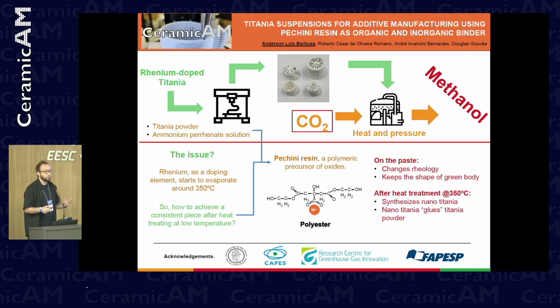And how does it work in our paste? First, this resin works as a rheological agent, changing the rheology and giving viscosity to the paste. After drying, it keeps the green part in shape. After burning at a relatively low temperature, we can burn it at like 350 degrees.